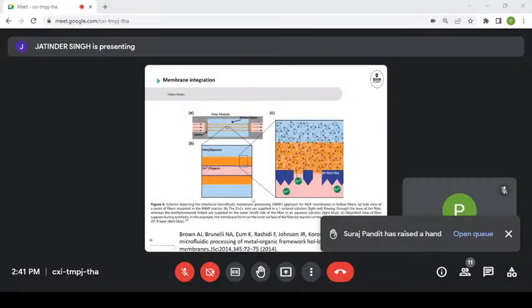So what happens is that one reagent for making the MOF sits outside in the chamber. The other one is pumped through the inside. They come into contact in this material, and that's where the outside of the hollow fiber material starts to become coated with the metal organic framework. So here the reaction takes place and the material is being formed.